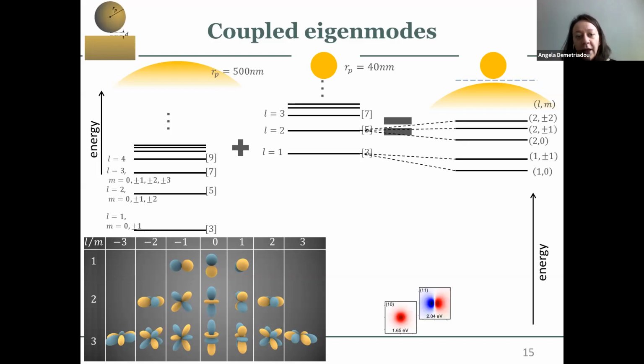Okay. And then the second order mode also splits its degeneracies. You have the 2,0 occurring at lower energies, and then the 2,1 are slightly higher, and the 2,2 are slightly higher energies. And here is how they look in the gap. So you have the 2,0 mode there, which has a plus, a 0, and then a minus. And then you have the 2,1,0, which is basically the second order of this one. And then you have the 2,2 mode.